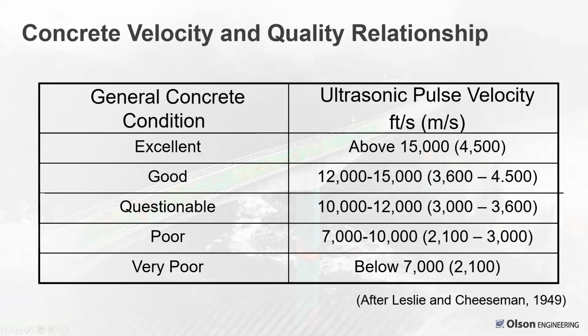So in general, and this was developed a long time ago as people first started to do ultrasonic testing of concrete after World War II: excellent concrete is above 15,000 feet per second, good 12 to 15,000, questionable 10 to 12,000, poor 7 to 10,000, very poor below 7,000 feet per second. So this is a general guideline. It's still a good reference. Obviously it varies with concrete.